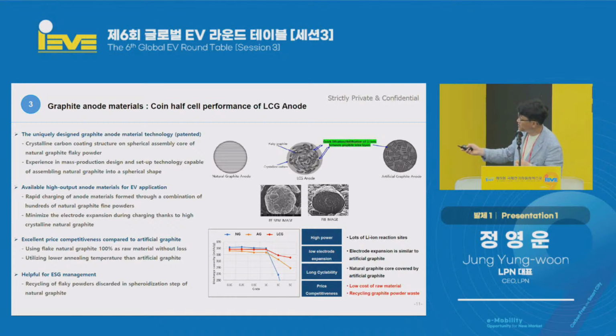But in the case of our graphite anode, it's just an amalgamation of small structures. But crystal itself is much better. Artificial graphite is crystallized over a long period of time, and it's difficult to control and fine-tune the microstructure. But if we pulverize one more time, the output would be much higher in our process, and we can also control and fine-tune this.